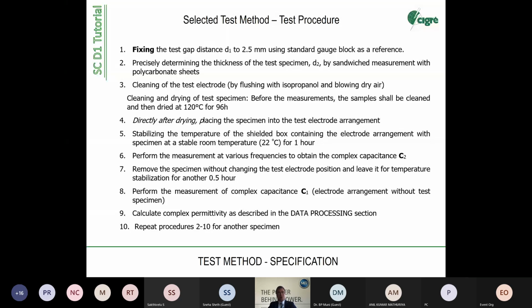And finally, we need also to standardize on data processing, because the first results that you get from Argentina look completely different and in a completely different format than the results you get from Canada. So we have made standardized Excel tables where you can fill in your data, at which frequencies and which number formats. And repetition, of course, is repeatability, and is an important thing. Repetition means repeating it in the same laboratory. So you should obtain the same result in repetitive measurements. And repeatable means if you measure it in Canada, it should be the same result as in Argentina.